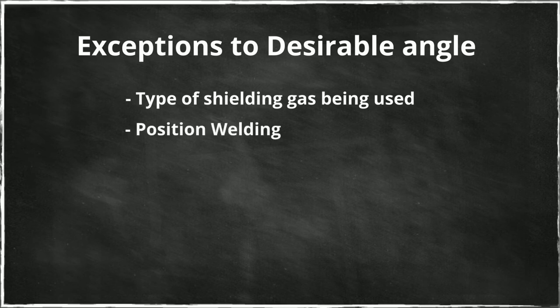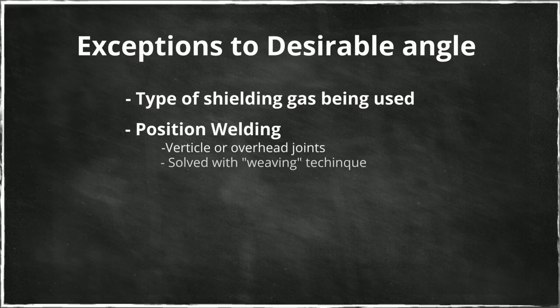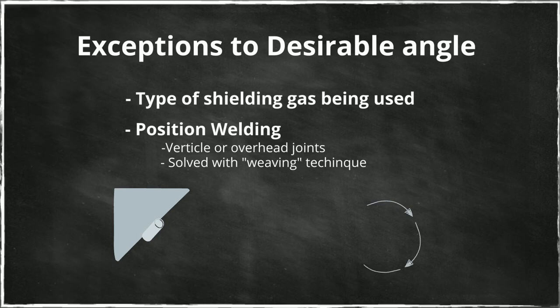Position welding. That is welding vertical or overhead joints may require the use of weaving technique to assure proper weld deposition and penetration. In position, gravity tends to cause molten metal to run out of the puddle, resulting in cratering and undercutting, two conditions that produce a weak weld. Weaving consistently moves the fusion zone around so as to limit the amount of metal being deposited into any one point. Surface tension then assists in keeping the molten metal in the puddle until it is able to solidify. Development and position welding skill takes a lot of practice but is usually soon mastered.